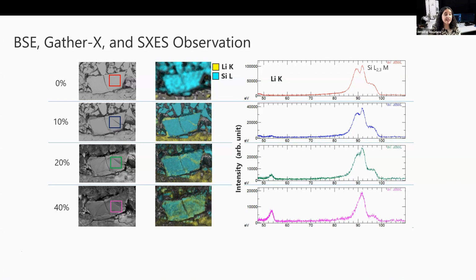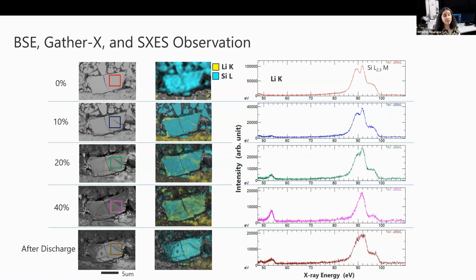At 40%, the silicon L peak shape has changed dramatically, and the lithium K intensity has increased even further. Also, the lithium peak position shifts to 53.4 eV, suggesting that the lithium is alloying in the silicon particle. And finally, looking at a fully discharged condition, the lithium K peak intensity becomes lower, and the silicon L peak shape is similar to that of amorphous silicon, indicating that the chemical state of the silicon particle has changed due to the lithium insertion and extraction. It can be assumed that some lithium remains in the silicon particles.